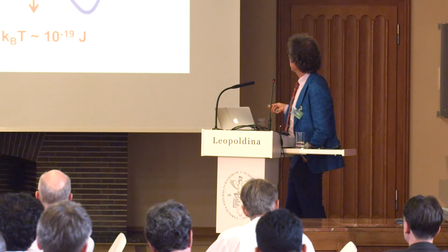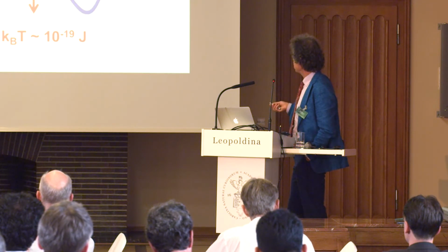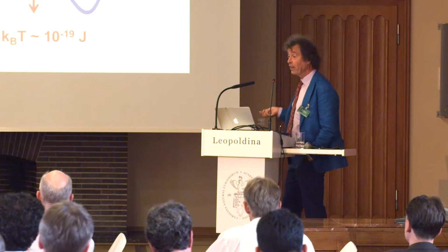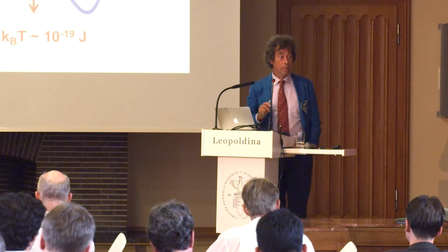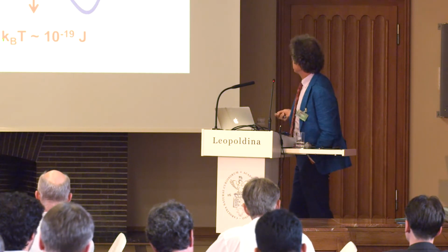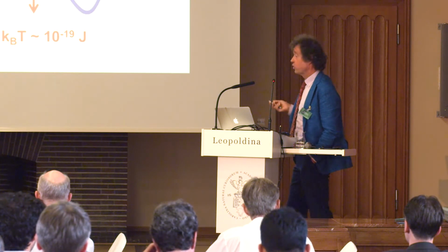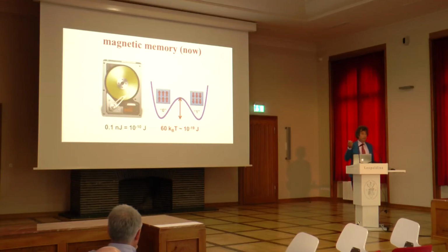And then, fortunately, there is an energy barrier between up and down, because otherwise it would flip all the time. And this energy barrier, if you want storage which stays at least about 10 years, the standard is about 60 kT. But 60 kT is only 10^-19 joule.